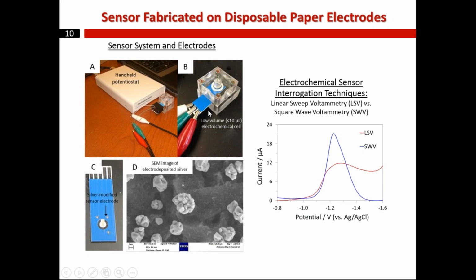We started by depositing silver onto the electrode by applying a negative potential to our electrode when the electrodes were inserted into a silver solution. And here you can see the SEM image for the deposited particles, showing that the deposited silver appears to have some particle shapes. After that, we started to